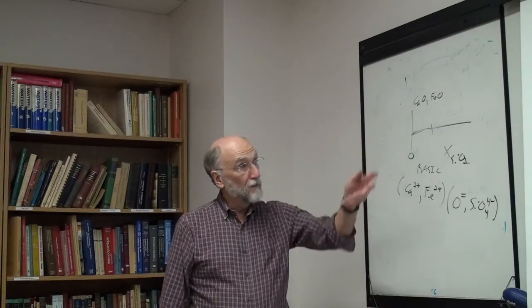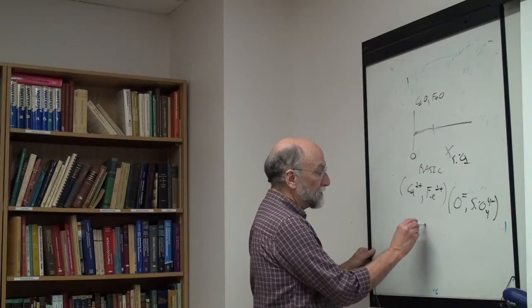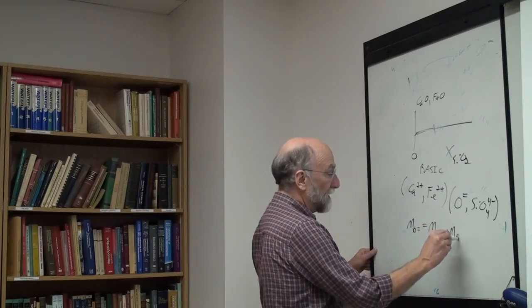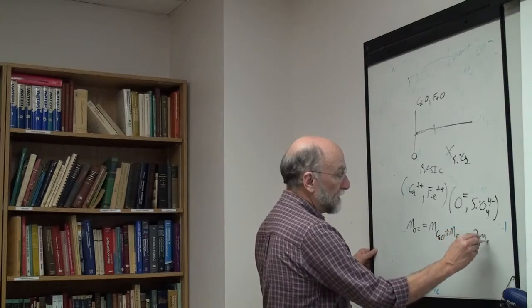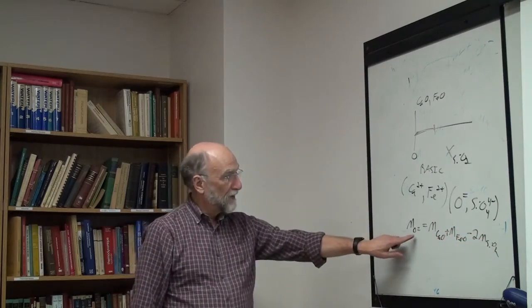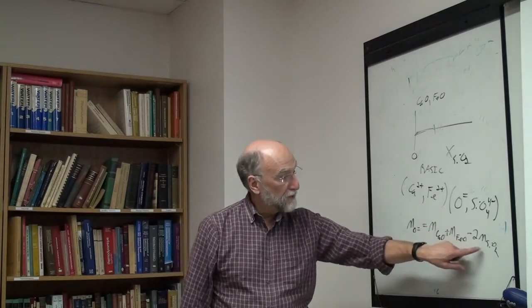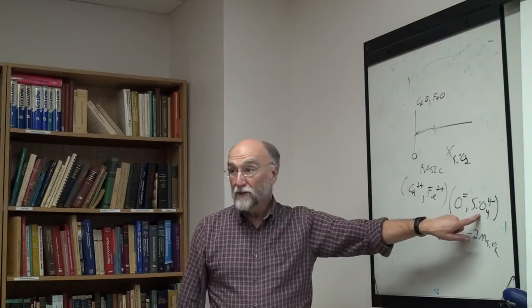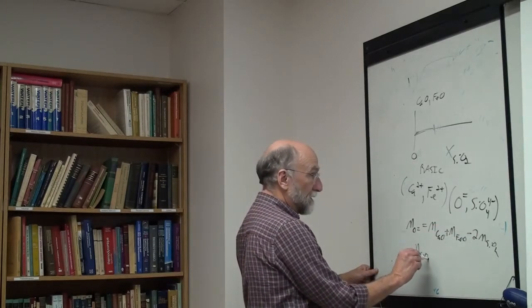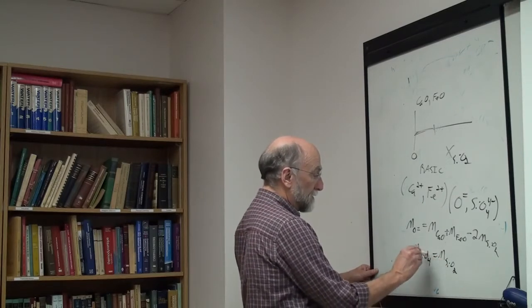So it's very, very similar to what we had before. And of course, the total number of oxygen ions will be the number of calcium oxides plus the number of iron oxides minus 2 times the number of silicons, because the total oxygens are supplied by CaO and FeO. And every SiO2 removes 2 oxygens to form an SiO4. And the number of moles of orthosilicates is equal to the number of moles of SiO2.